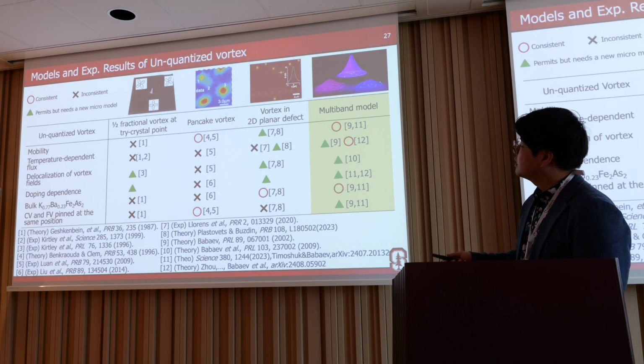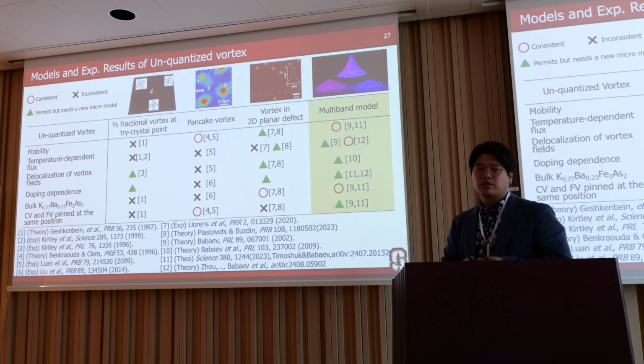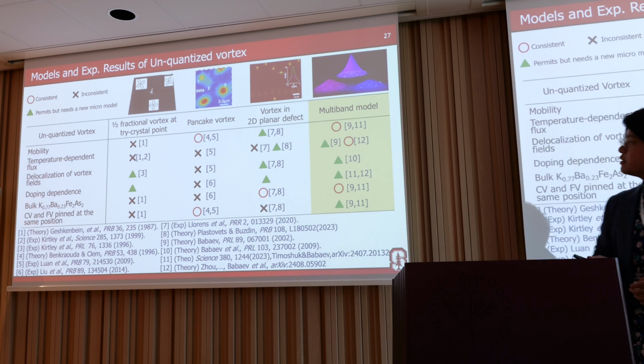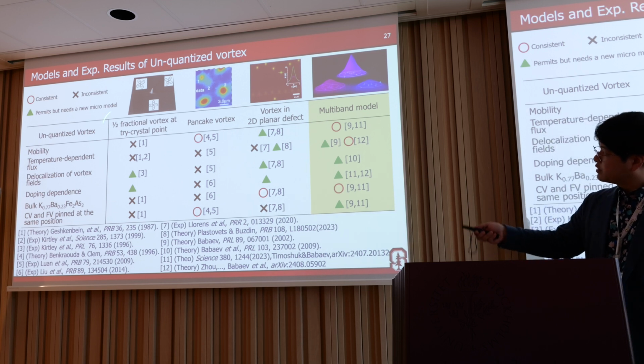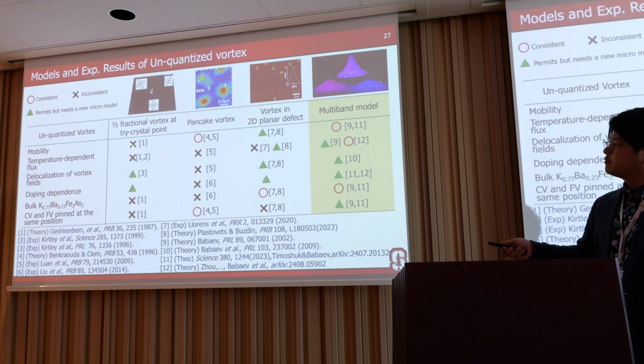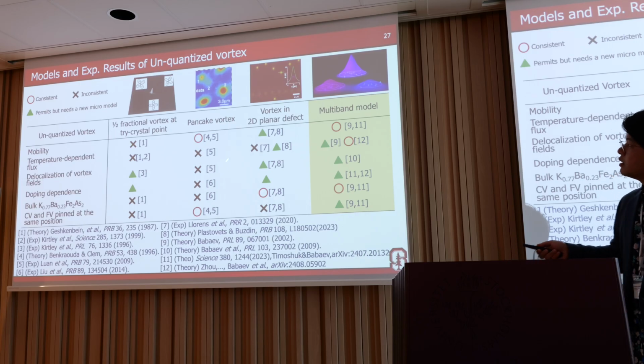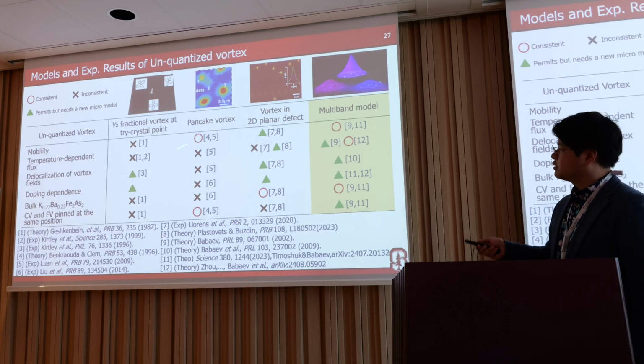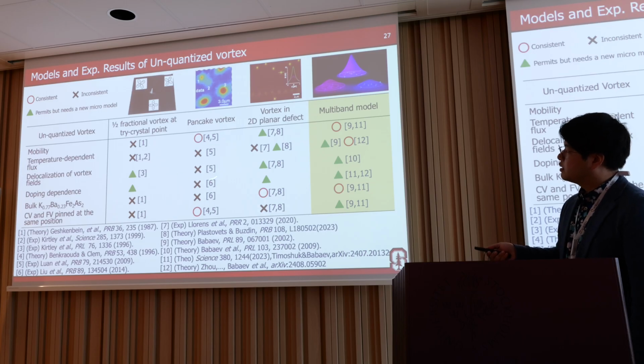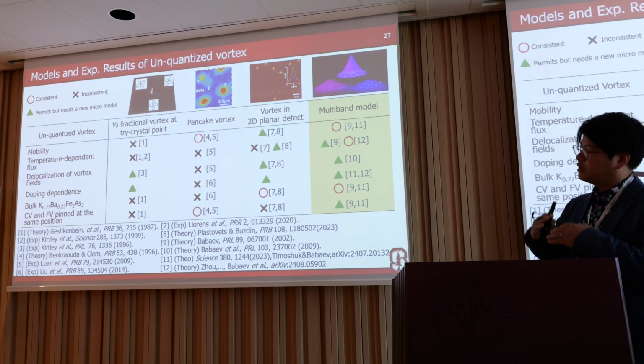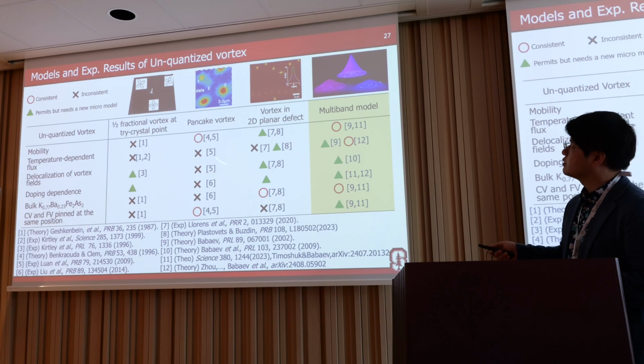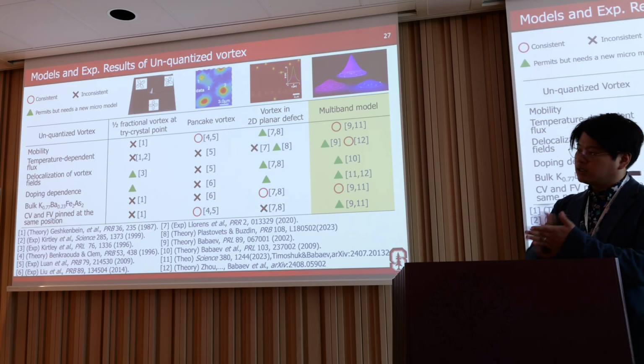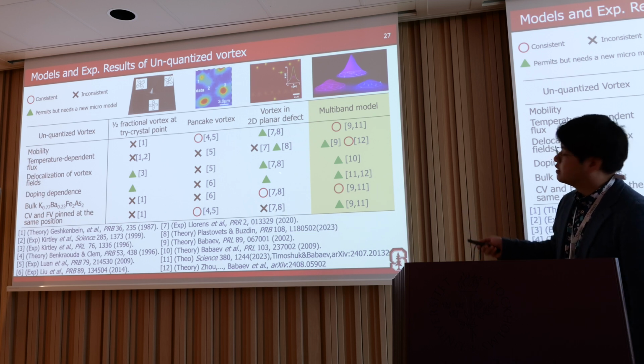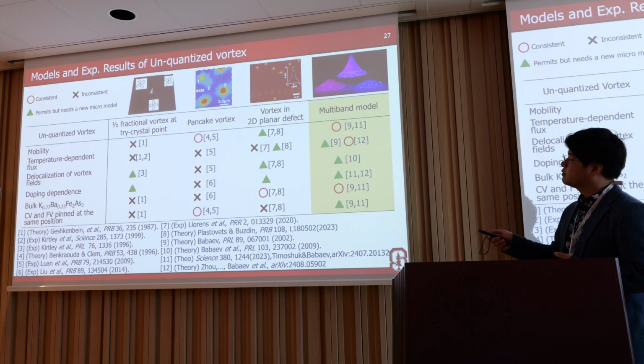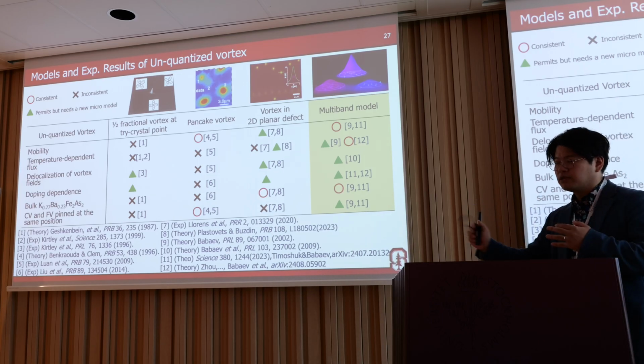Okay, so let's compare the existing models with our experimental result. For the half-integer vortex at a tricrystal point in a D-wave superconductor, there is an obvious difference in mobility and temperature dependence. A pancake vortex is mobile, but its temperature dependence and delocalization are not consistent with our case. Also our material is not so highly anisotropic, so this is not our case. And 2D planar defects get similar delocalization, and if it is a very complicated 2D planar defect, maybe it also looks mobile.